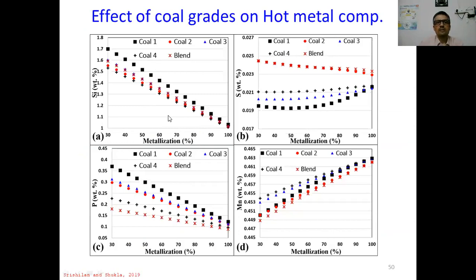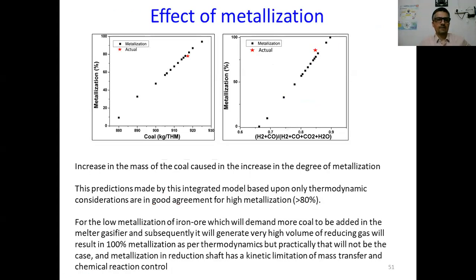The reason is very much obvious, that higher metallization will require lower coal. So it means that a lesser amount of ash is being added into the system. So obviously you will have lesser silicon content in the hot metal also. A similar kind of trend you can see for phosphorus also, and manganese also. So under different conditions, with different types of coal used, we can predict the liquid metal composition also.